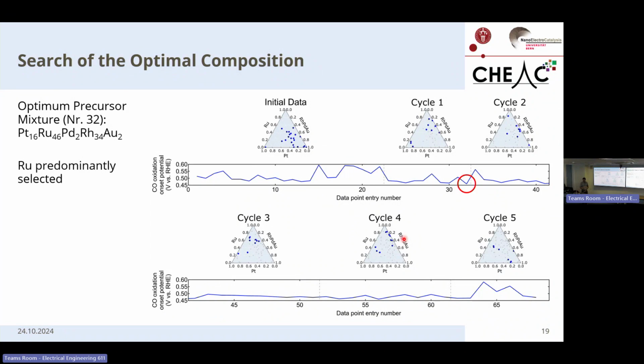In subsequent cycles, we see that the optimization algorithm is suggesting samples rich in ruthenium. And thereby we see that the CO onset potential is more or less stable and is the most active. In the last cycle, we decided to manually add samples which have a low amount of ruthenium to verify whether we have converged or there are some unexplored regions. And as these samples yield a high onset potential, we decided that we converged and we indeed found our global optimum.